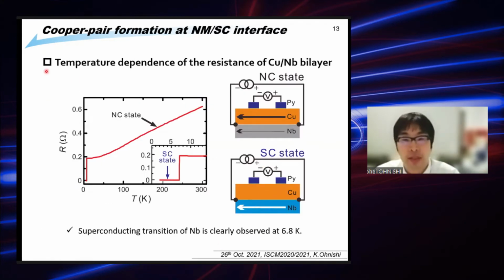Using these samples, first we measure the temperature dependence of the resistance of the copper-niobium bilayer. The result is shown here. From this, we can estimate the superconducting transition temperature. Because in the superconducting state, of course, all of the charge current flows in the niobium layer, the resistance should show a drop like this. From this result, we can estimate that in this sample the superconducting transition temperature is roughly 6.8 Kelvin.